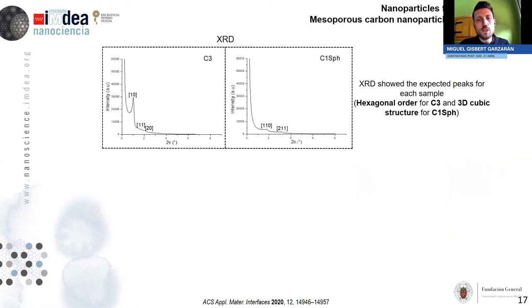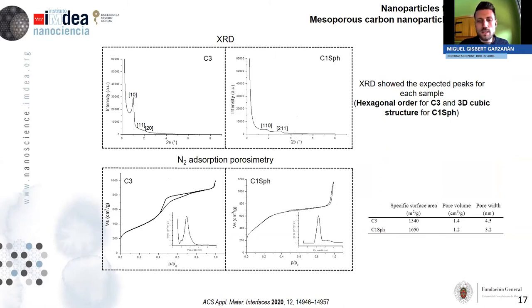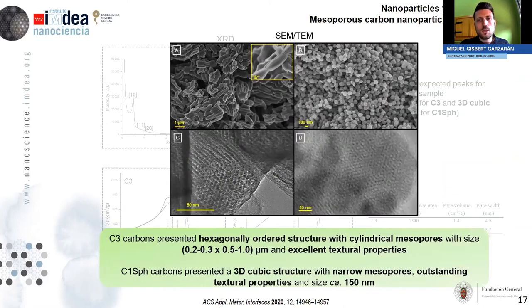for this work. Okay, so these carbon nanoparticles can also be characterized using more or less the same techniques. They also present symmetry at the pore level. They have these great textural properties that I was saying, and also they can be visualized using different electron microscopy techniques. So in the end, we can conclude that we have the C3 carbons that have a hexagonally ordered structure with cylindrical mesopores that are in the micron size and that present excellent textural properties, and also that we have these C1 carbons with a three-dimensional cubic structure with narrow mesopores, excellent textural properties as well, and a size of around 150 nanometers.